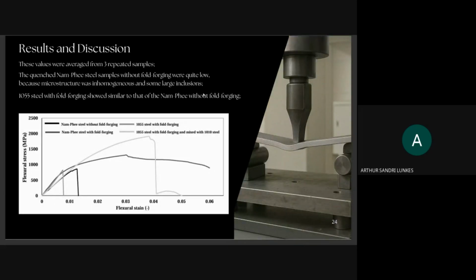So now we have the results and discussion for the three-point bending test. The values were averaged for three repeat samples, and now we can see on the graphic that the Nam Phee steel without forging process and the 1055 steel with fold forging are very similar. It's the lowest flexural stress and the lowest flexural strain, these two tests here. And for the Nam Phee steel with fold forging process, we obtain the highest value of flexural strain and the highest flexural stress we obtain for the bending test.